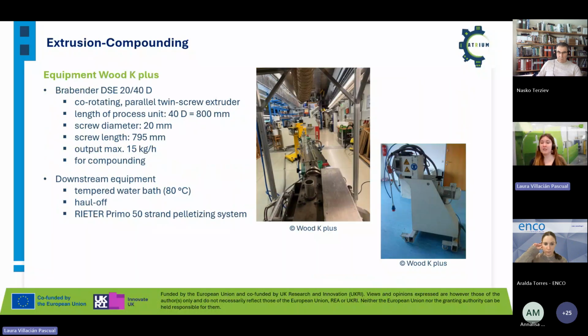In the ATRIUM project, as commented, as we have two different partners, we have different equipment as well that is being used. From one side, we have the equipment from Wood K plus, which is a Brabender co-rotating extruder, and the length of the process unit is 800 millimeters, and the screw diameter is 20 millimeters. The maximum output is 15 kilograms per hour for compounding, and the material goes down into a tempered water bath of 80 degrees Celsius.